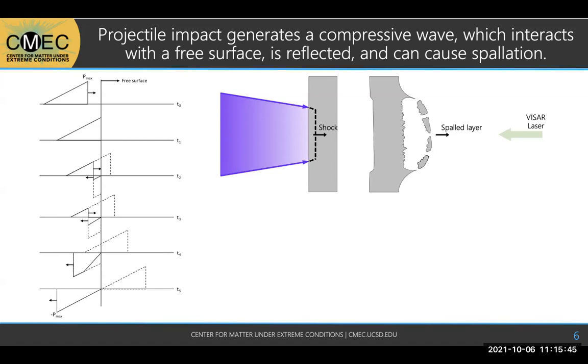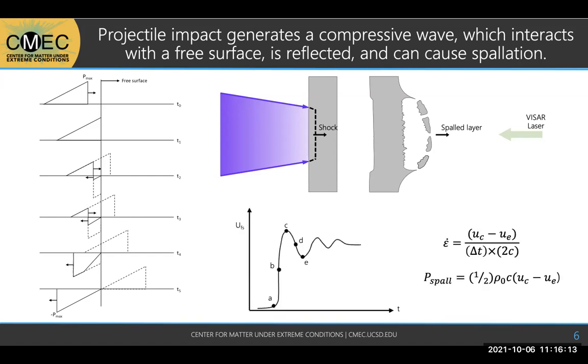A lot of spall experiments also happen with gas guns, because you can get really nice big samples with a lot to analyze, whereas in laser shock you're really limited to really small bits, and it's hard to recover material. So from the VISAR, or the velocimetry, next, there we go. Yeah, we get a curve that looks like that. It's a pretty simplified, characteristic spall velocity curve, where I'm going to describe each point right here, and then we can tie that to the equations.